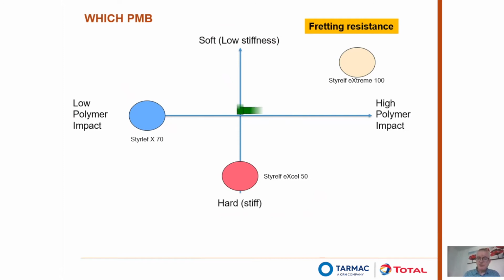So again, if we look at where the impacts are going to be improved, it's again towards that high polymer impact, and again towards the sort of lower stiffnesses. Because if the material's too stiff, and a fast force is applied to it, that bitumen is likely to fracture, and you'll lose your surface aggregates. So again, the Styrelf X70 is not going to be great at resisting fretting. Your Styrelf eXcel 50 will contribute to it because it has a better polymer impact than the Styrelf X70. So it's a small tick in there. But of course, your Styrelf Extreme 100, because of the high polymer impact, will have a big tick in there.